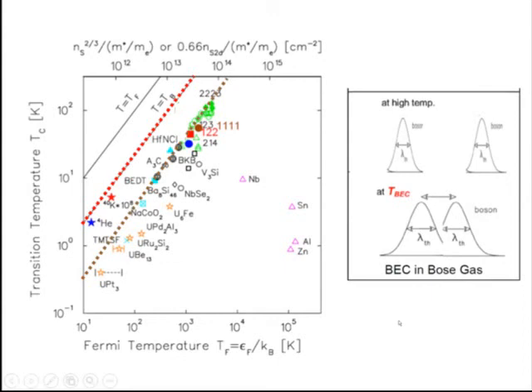In real superconductors we are seeing, the actual TC is lower by a factor of four or five from this hypothetical Bose-Einstein condensation temperature. This is, in my opinion, due mostly to competing magnetic order, and also low dimensionality can lower TC. Today, I will show at least two observations that place actual data points on this dotted red hypothetical BEC line.